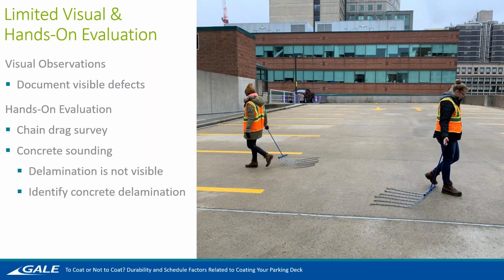So with that, on the wearing surface, we use a chain drag survey. The photo on the right shows chain dragging up and down the wearing surface of a garage. The way we pick out if concrete is delaminated or if it's sound is that sound concrete will give out a ping sound, and delaminated concrete will sound hollow. Similarly to the chain drag survey, for the overhead surfaces, we will use a hammer and basically just sound around areas that might have rebar rusting coming through or efflorescence showing to determine if it's actually delaminated.